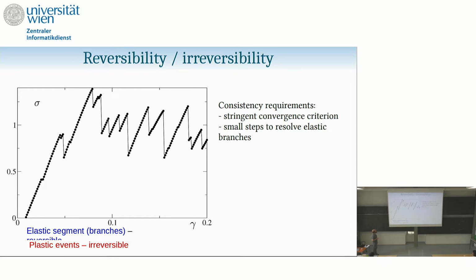So we will speak about elastic segments or elastic branches to refer to these parts of the stress response which correspond to the adiabatic tracking of local minima. And then we have what are called plastic events, which are these jumps. Okay? So there are consistency requirements to do that in a proper way. First of all, you need to minimize the energy accurately. There is a hidden parameter, which is how well you minimize the energy. And there is another parameter, which is the steps you take. Let me say for now that the steps you take must be small enough that you resolve this continuous response of the local minima.